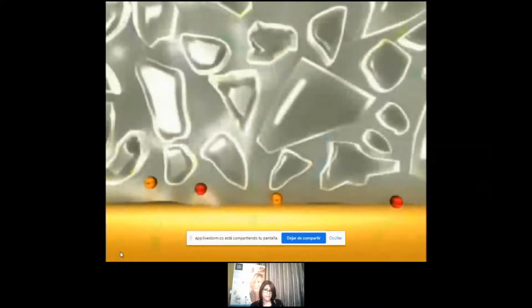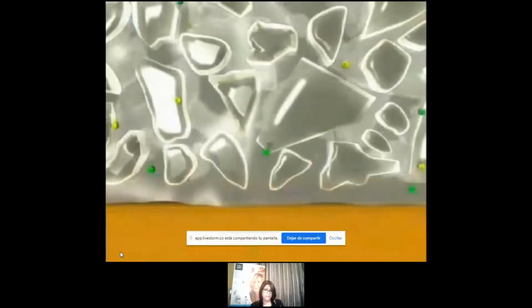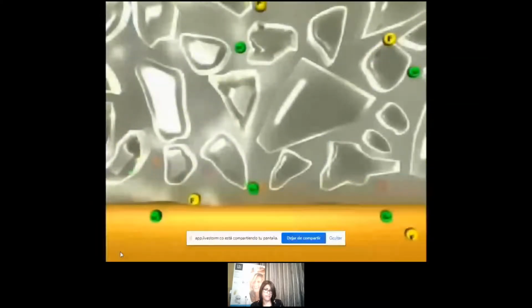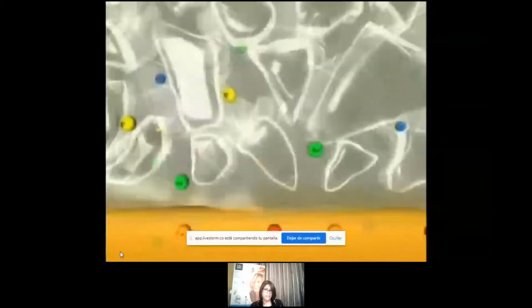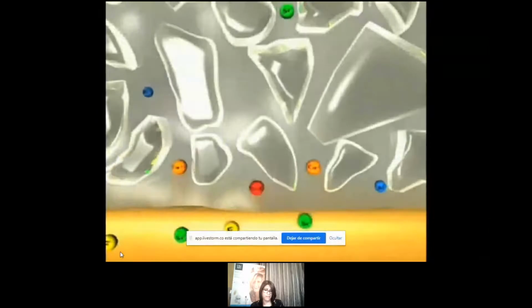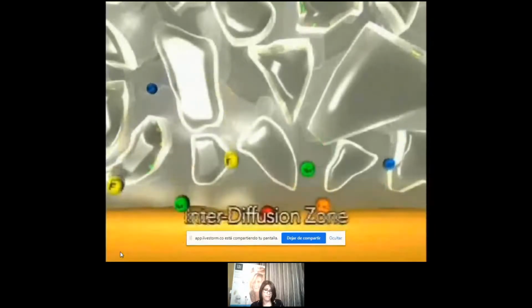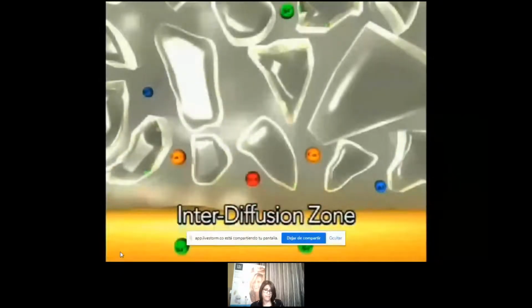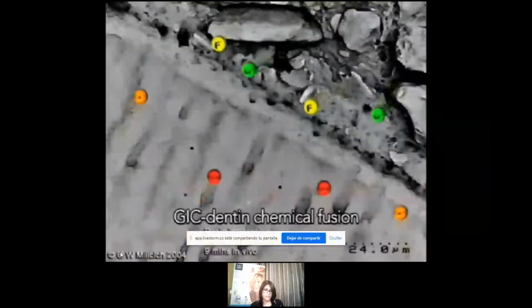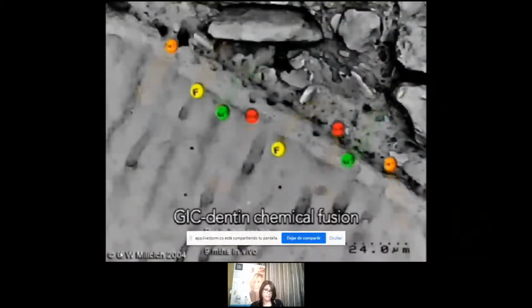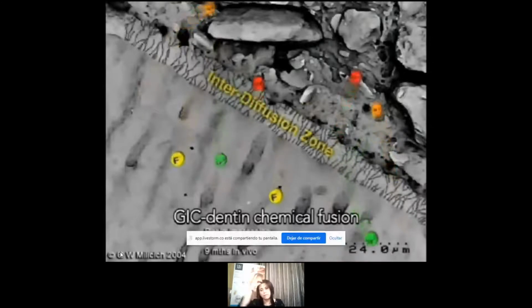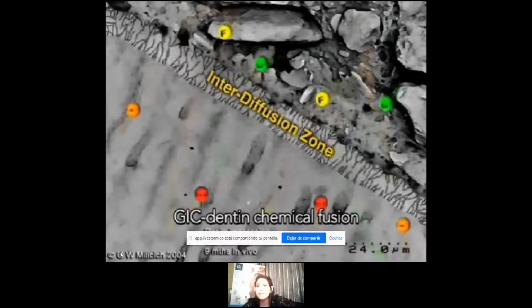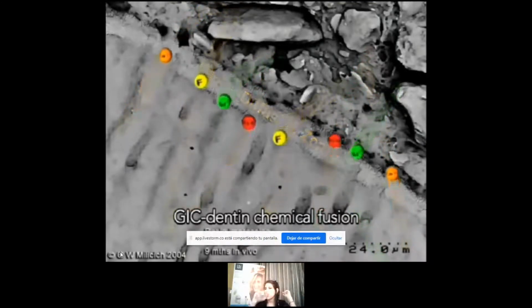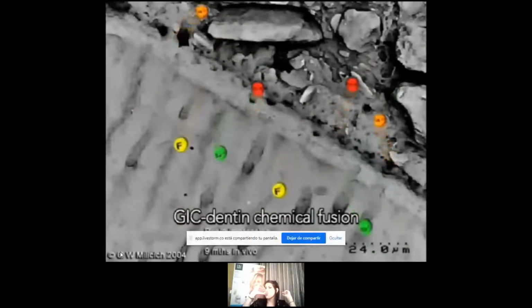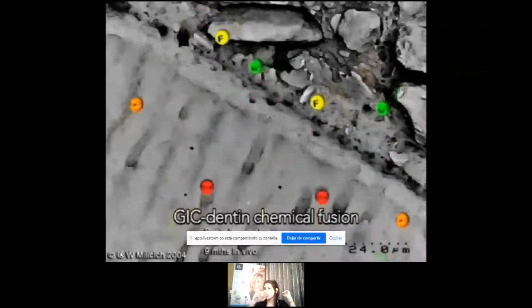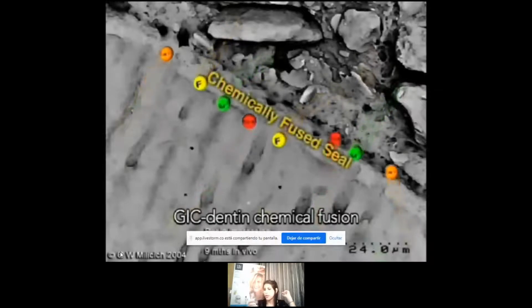Calcium and phosphate ions from the polyacid-treated dentin and enamel, and strontium and fluoride ions from the unset glass ionomer intermix and precipitate, forming an interface called the interdiffusion zone. This zone is stronger and more acid resistant than either the glass ionomer or the tooth. The combination of the interdiffusion zone and the chemical bonding provides the basis for a strong, stable adhesive interface and creates a bacteria-proof seal for the cavity, best described as a chemically fused seal.